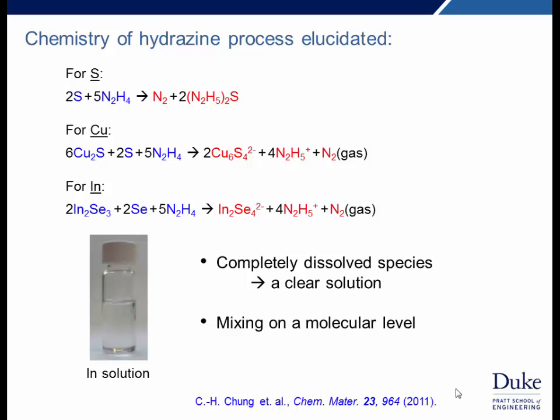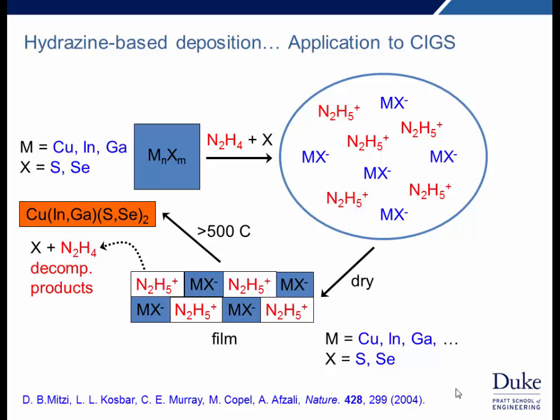But the main thing is we're getting mixing on a molecular level, and this is important when it comes time for a thermal treatment. It means we can do the thermal treatment quite quickly. We don't need to have long annealing sequences, which will give opportunity for volatile elements to disappear. And so if we take our solution, we can solution process it into thin film form. If we heat it up above 500 degrees C, we can generate our CIGS film with adequate grain structure.